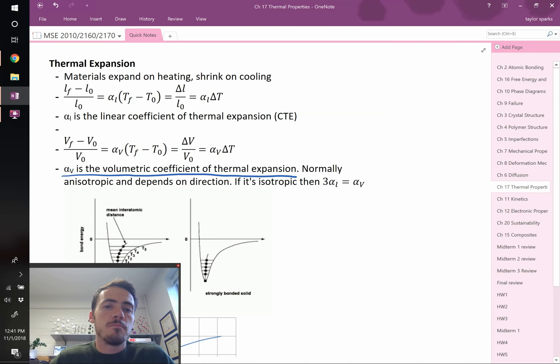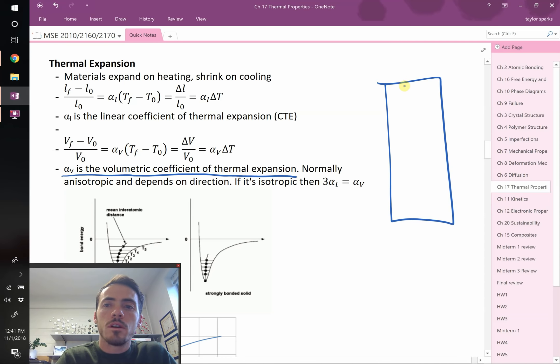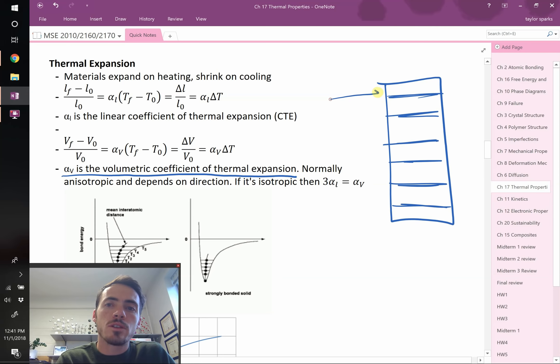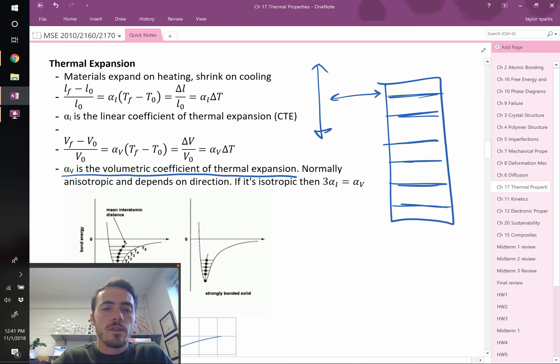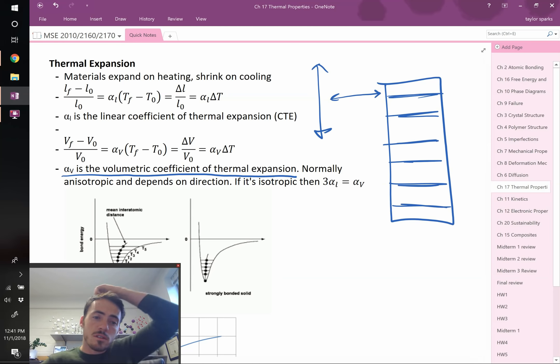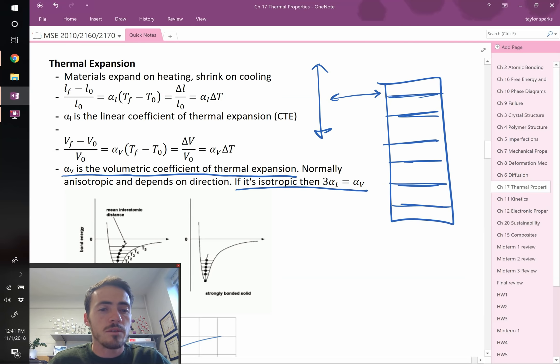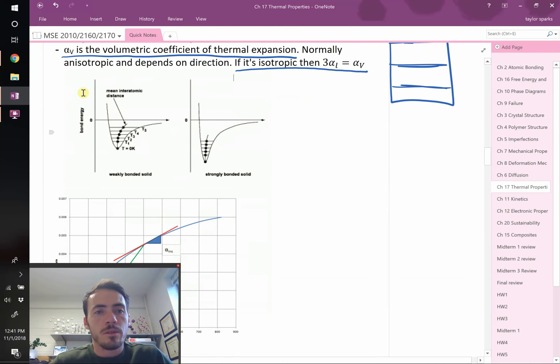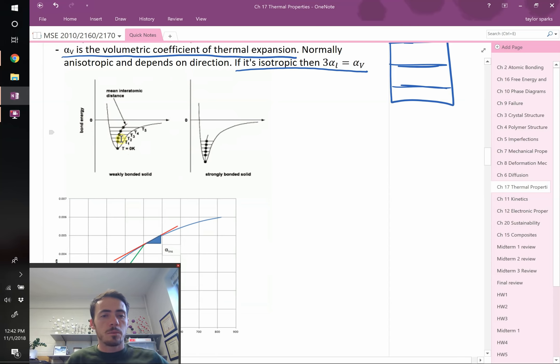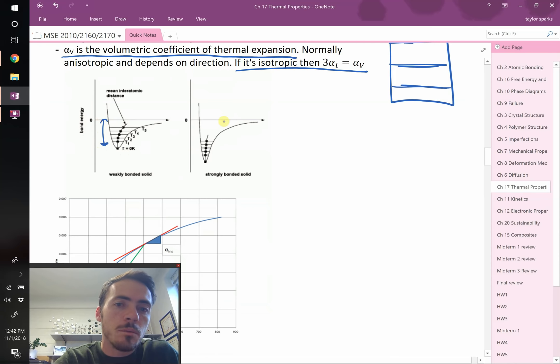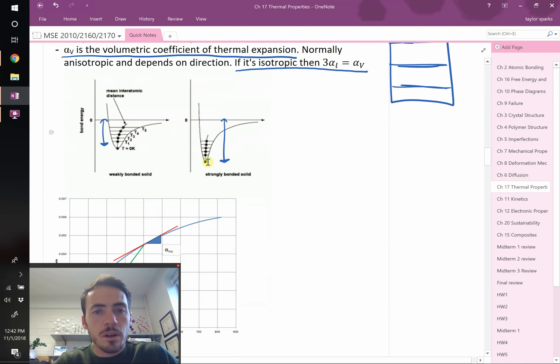If your material is anisotropic — like graphite with planes of carbon atoms — you'll get very different expansion in-plane versus transverse to that plane. For isotropic materials like silicon or diamond, expansion is the same in all directions, and we can approximate the volumetric coefficient of thermal expansion as simply three times the linear value. Thermal expansion comes from the energy potential well diagram — strongly bound materials with deep wells tend to be more symmetric and show less thermal expansion.